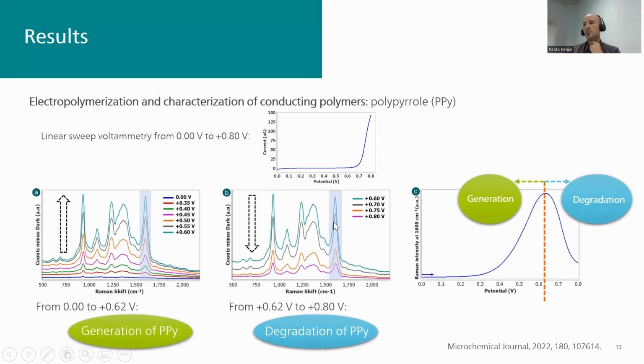So it provides us a lot of information, and that is not provided just in the cyclic voltammetry. Because in fact, if you look at the cyclic voltammetry from 0 to plus 0.6 volts, it seems that nothing is happening. So we don't have any electrochemical process. However, we can follow with the Raman spectra that the polypyrrole is being generated. And in fact, if we carry out several voltammograms between 0 and plus 0.6 volts, we can increase the thickness of the polypyrrole that is generated. However, if we go to higher potentials, we are over-oxidizing the polypyrrole and we are losing the structure.